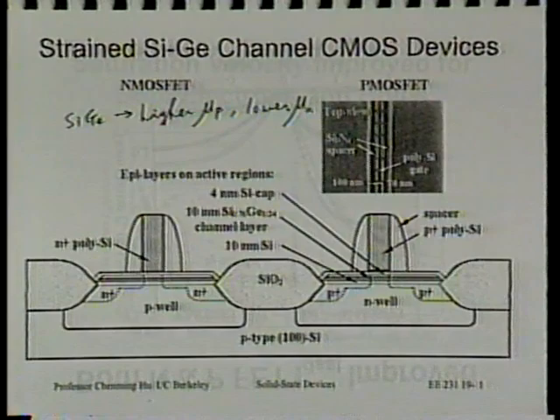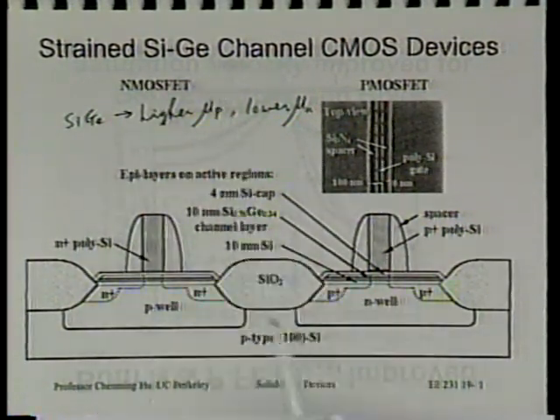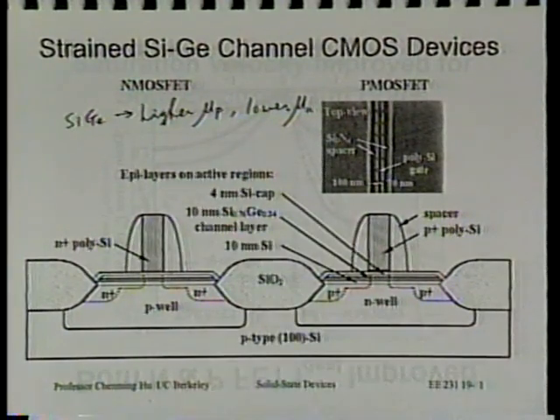Okay. Secondly, I want to point out what's meant by strained silicon germanium. Now, it turns out the mobility, the transport property, has to do with the strain in the material. And when you grow epitaxial silicon germanium on silicon, because the lattice constants of these two materials are not the same, the silicon germanium is under strain. All right? And the strained silicon germanium has this property. Okay?